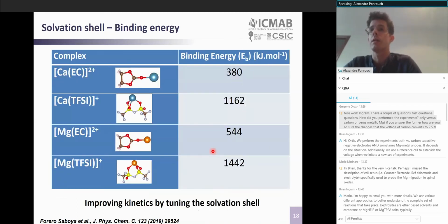So we expect that the formation of these contact ion pairs will have a significant impact on the plating and stripping kinetics. So here I'm showing the binding energies for different cation complexes. The binding energy is basically roughly proportional to the desolvation energy, an energy that we will have to pay before any plating or insertion event can take place. So of course, the higher this binding energy, the lower the process kinetic is expected.